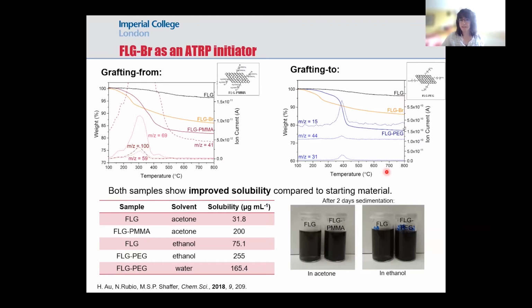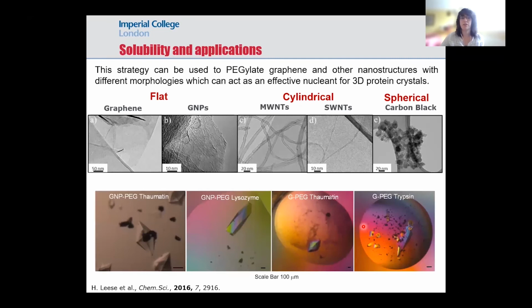So the dispersibility, the solubility of these graphenes improve significantly compared to the starting material, in acetone and ethanol after 2 days sedimentation, which is good for further applications again. So these pegylated graphenes can be efficiently used as nucleants for 3D protein crystals. These different carbon nanomaterials have been pegylated in this work, using graphenes as flat structures, cylindrical structures such as multi-wall or single wall, or spherical nanostructures such as carbon black. The best nucleant for 3D protein crystals that we observed was the graphenes that contain this PEG chain.